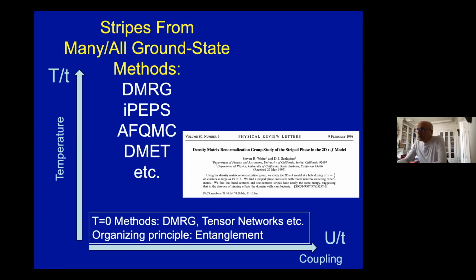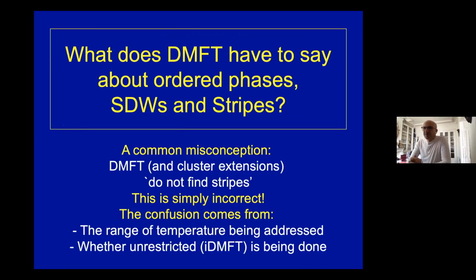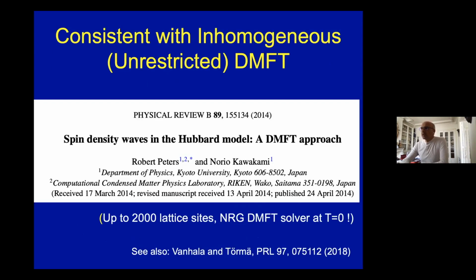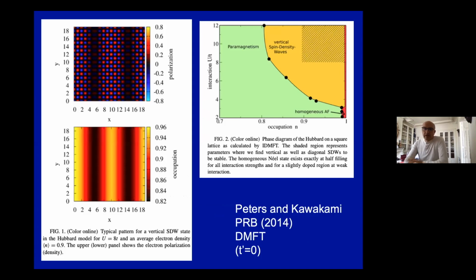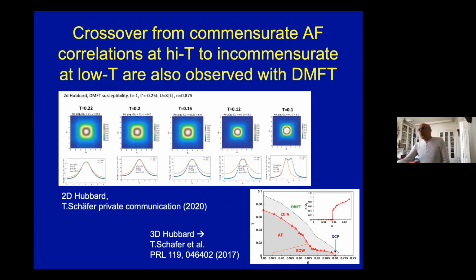And by the way, this is a very well-known paper about this. And by the way, this is also seen by dynamical mean field theory. It's actually a common misconception that DMFT and cluster extensions do not find stripes. Actually, this is not correct. The confusion comes from the range of temperature being addressed, and most importantly, by the fact that often DMFT is looked at in a restricted way, not in the sense of unrestricted mean field, where you allow each site to do whatever it wants. There is a beautiful paper by Peters and Kawakami that I show here that demonstrates that you do find, even within single-site DMFT, beautiful stripes forming at zero temperature in the Hubbard model. So how do we reconcile all that?